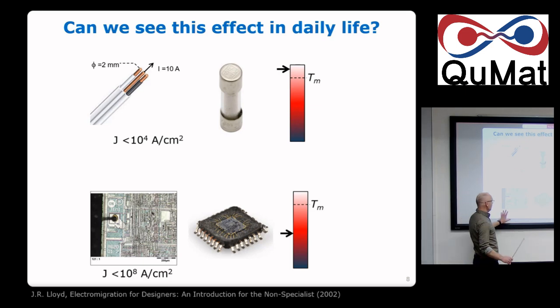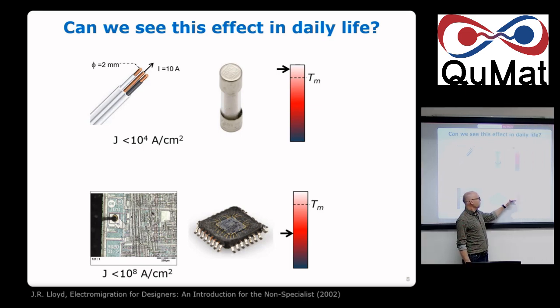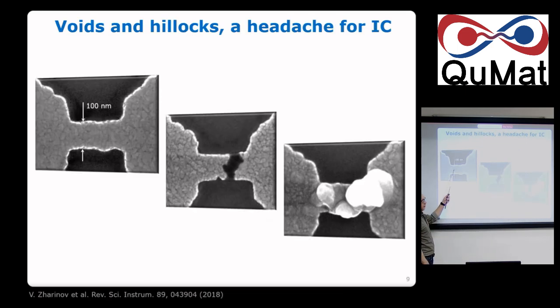So what happens with electromigration? Basically you apply a very high current density, answering your question, of this order of magnitude, and you are far below the melting point. Okay, you are heating up, of course, but you are far below melting, and you start moving atoms. This is how the system looked before moving atoms, and you can end up either moving them away completely or actually piling them up. That depends on the conditions.